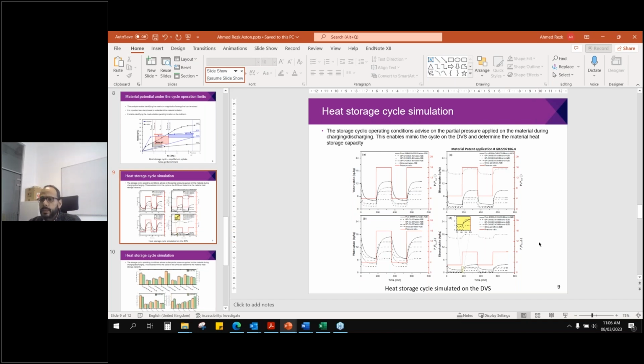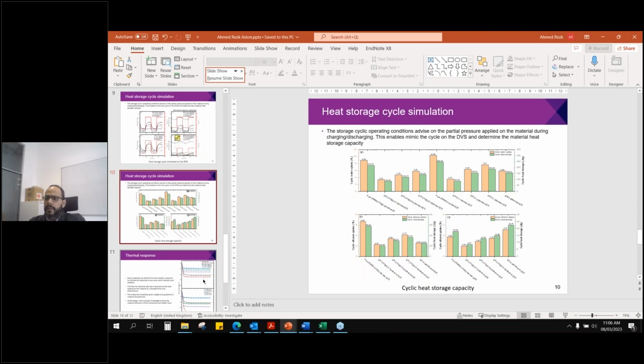We show how we use the material as the equipment capacity to study this material. And now we know how much uptake and how speed this uptake happens, so we can quantify almost how much heat can be stored in this heat storage application. As you can see, when we did this analysis, we used change in the partial pressure. We didn't consider actually the heating and cooling, and the main purpose of developing this composite was to stimulate the heat transfer to aid or support the sorption potential.